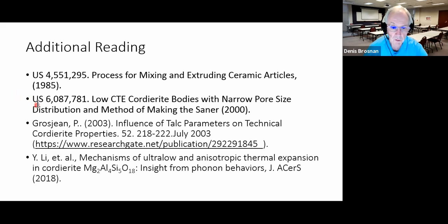And this one here, they're developing cordierite with very narrow pore size distributions, and I believe they were actually adding some magnesia, some excess alumina in the composition to reach those narrow size distributions.